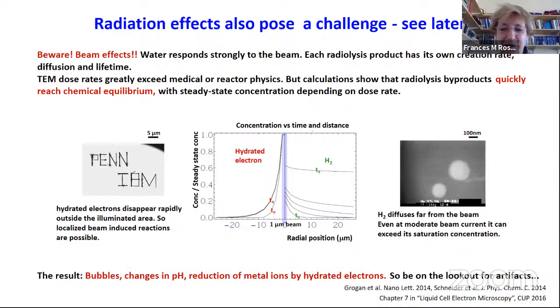You get radiolysis, you can form things like hydrogen, you can change the chemistry by creating hydrated or solvated electrons. You can use those effects to reduce metal ions, and you can scan the beam. These effects are localized within the beam, and you can even do some little writing exercises. So I put this one in just for fun because you can see we were operating this by hand. It's not really programmed. As we scan the beam around, the changes in chemistry caused by the beam result in precipitation of individual gold atoms from gold ions in solution, and you can use it to write the names of your institutions. That's what people tend to do.